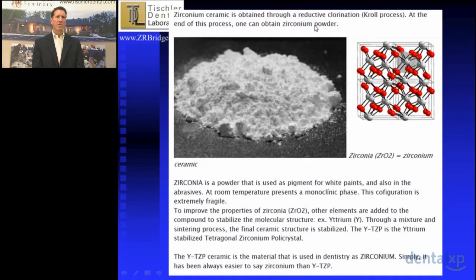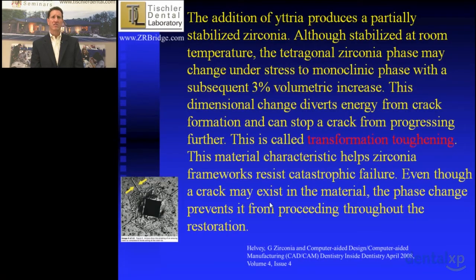So this reductive chlorination process produces a white powder, and then certain binders and strengthening agents, such as yttrium, which is another element, are mixed with the zirconia powder. Now this is made into a ceramic zirconia block that is quite a bit stronger. Because of the yttria added to the zirconia crystals, there's quite a bit of strength incorporated. One of the benefits of zirconia, and why it is so strong, is that it undergoes something called transformation toughening when there's any kind of fracture stress on it. And it's the yttrium that allows this non-propagation of cracks in zirconia to occur.